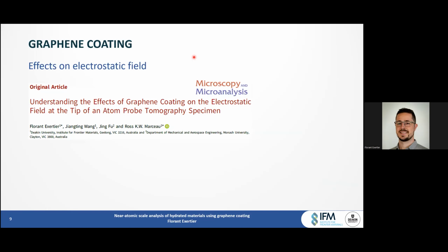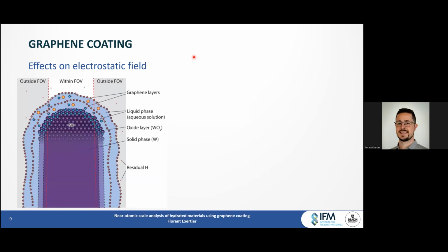So the first step of this study was to analyze pure tungsten coated with graphene to try and understand the effects of graphene coating on a well-known test material. So this is a schematic of what the sample looks like prior to atom probe analysis. So we've got a layered structure with the tungsten, a thin layer of oxide, and then the water, graphene, and then repeat with additional graphene layers.